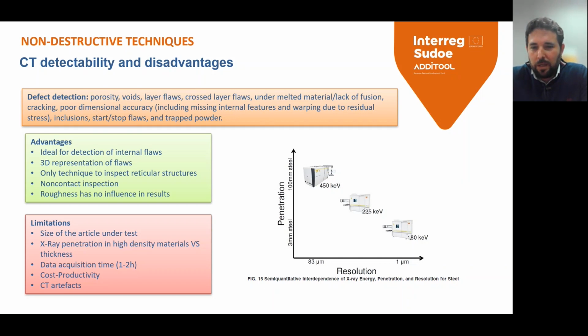Also, it's the only technique capable of inspecting lattice structures, and roughness has no influence on the results. On the other hand, one big limitation is the maximum size of the part to be inspected. For that reason, it's not the best option when inspecting parts manufactured by DED, and it is also more expensive and slower than other techniques.